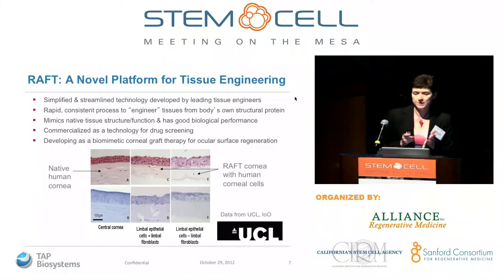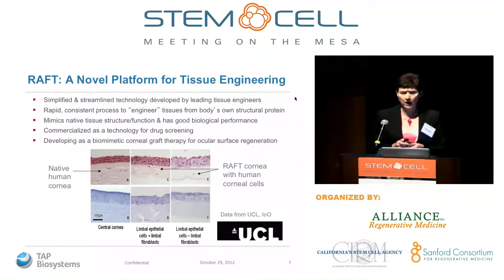What was discovered by Professor Robert Brown, a tissue engineer in London, was that if you took a collagen hydrogel and put it in contact with something absorbent — he started with lab paper towels and moved on to Whatman's Number 1 filter paper — some of the liquid would move out of the hydrogel into the absorbent material. In one simple step, this concentrated the cells and collagen from a very weak hydrogel at about 0.5% to a physiologically relevant collagen concentration of around 8–10%, with cells still present at high viability.